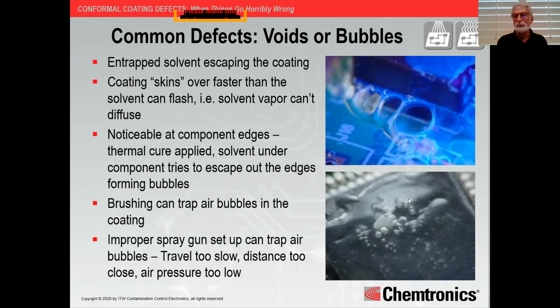Those are especially common. Now, if you're brushing, when you dip your brush in the coating, it can trap bubbles between those bristles. And then when you make your pass with your brush, it releases that coating with the entrained air bubbles in there. Sometimes those bubbles will dissipate as the coating levels out, and sometimes they become trapped. So that's a condition to warrant further inspection.